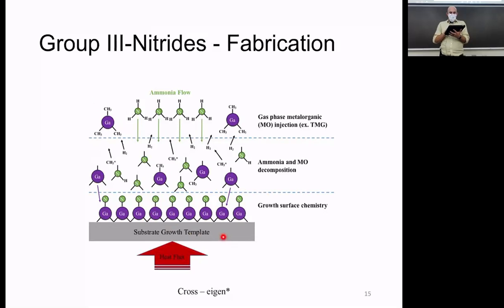We'd heat them up, so we'd give them energy to break them apart. So we'd split off the methyl groups. We'd break up the ammonia, and we would get a layer of gallium with nitrogen forming on the bottom. And the goal is to form multiple layers of this material. And chemical vapor deposition, or MOCVD, is very good at doing that. We can get growth rates on the order of microns per hour. Now, that doesn't seem very fast, but in the crystal growth world, it actually is pretty fast.